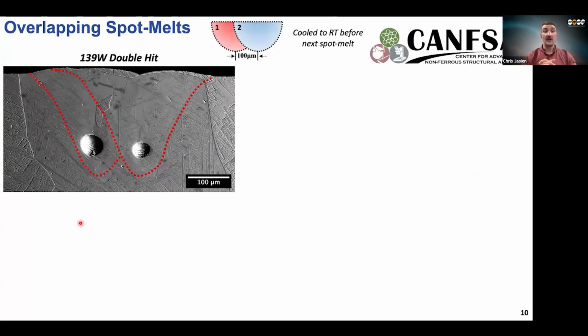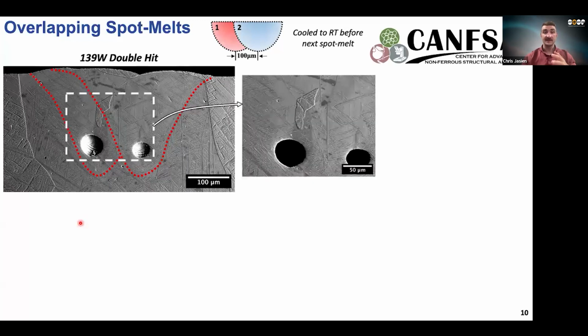So here we have this case where we have two overlapping spots, and we zoom in on this boundary where we'd expect the largest amount of thermal fluctuations. And what we can see is that as we move up this boundary, which is the boundary between the first and the second melt pool, we see a gradual decrease in the amount of this alpha double prime or TRIP product.